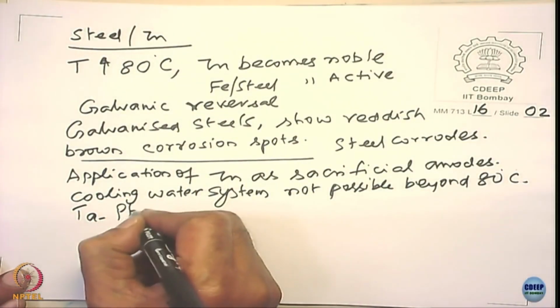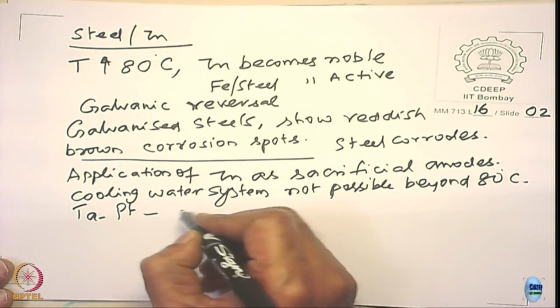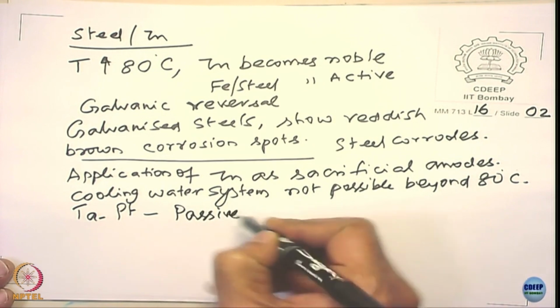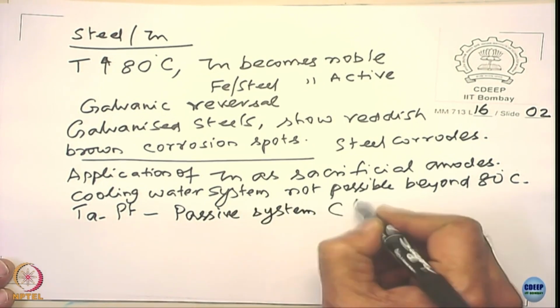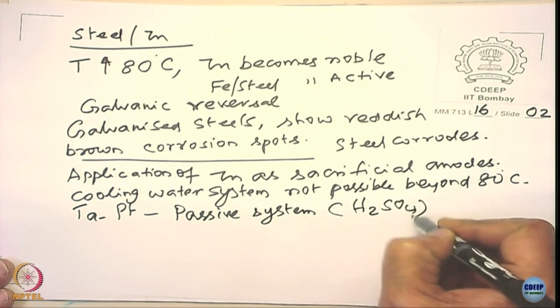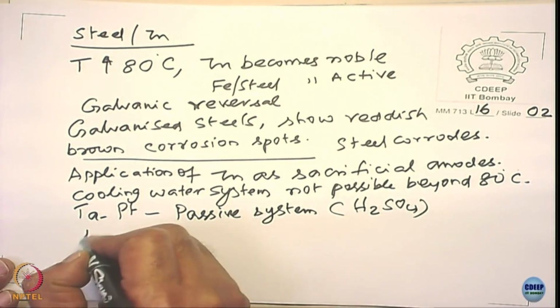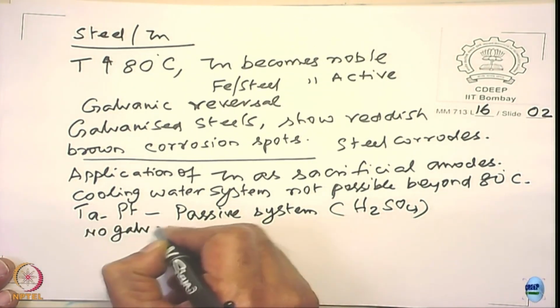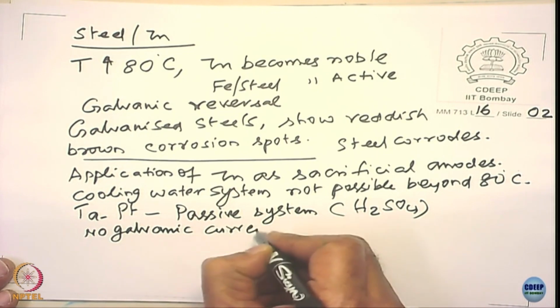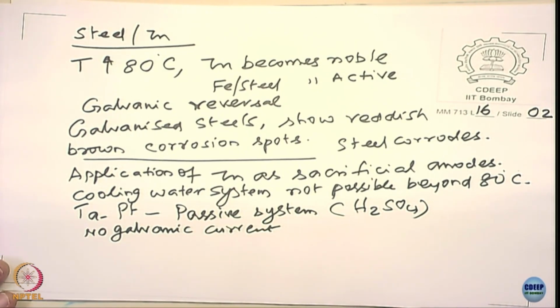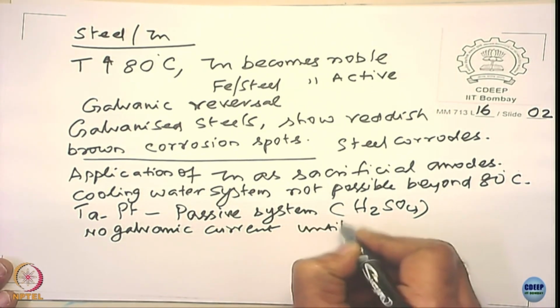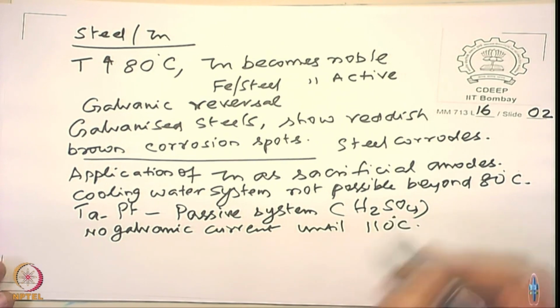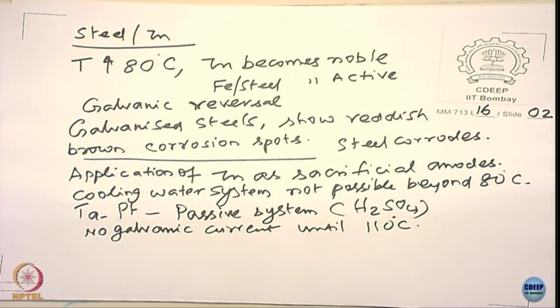There are a few more examples which are in fact very interesting. You take tantalum and platinum. This is a passive system. Let us say this is sulfuric acid, right, and you do not see any galvanic current, okay, until 110 degrees Celsius temperature of the sulfuric acid. You have no problem, you can have platinum and tantalum coupled together, you do not get any galvanic corrosion rate at all.